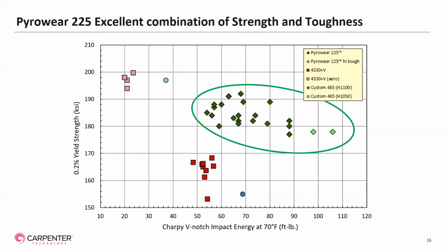So in this graph, what we've done is we've plotted the 0.2% yield strength versus the Charpy V-notch impact energy of Pyrowear 225 and compared that to other alloys that you may be familiar with, including 4330 plus V and our own custom 465, given 2 different heat treatments. The pink squares in the upper left of the diagram are the 4330 plus V that have been heat treated for aerospace applications, that is a relatively low temperature.